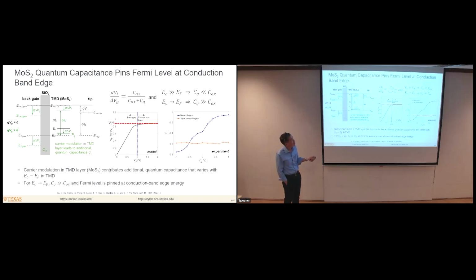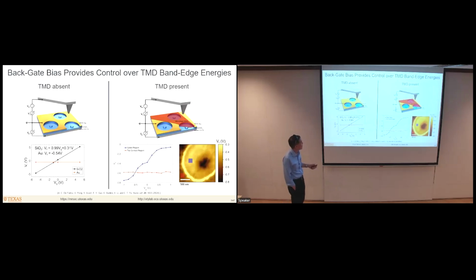And if we actually do that measurement and look at the dependence of the measured surface potential through the tip voltage on the gate voltage, then in fact it shows exactly this kind of behavior, right? And we can show that that is specifically associated with carrier accumulation in the TMD layer, because if we do the measurement without the TMD layer present, then the surface potential exactly tracks the gate voltage. But then once the TMD layer is present, then we get the behavior that I described and showed over here. All right.